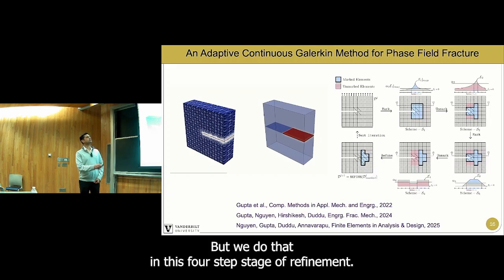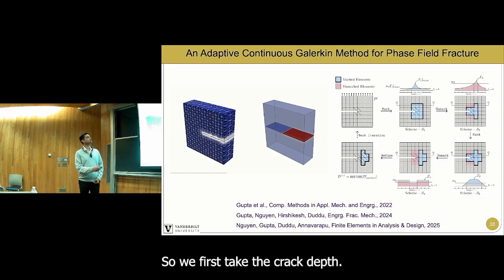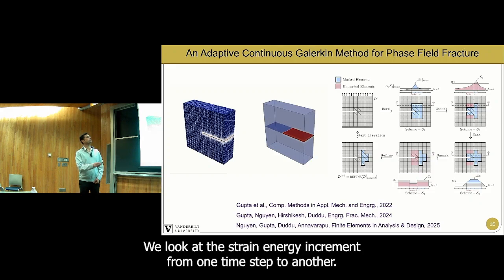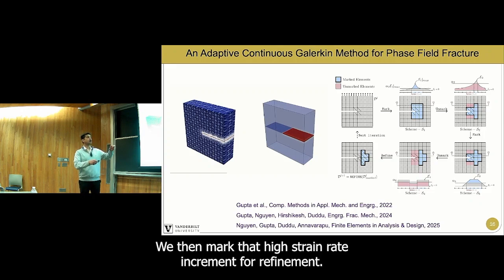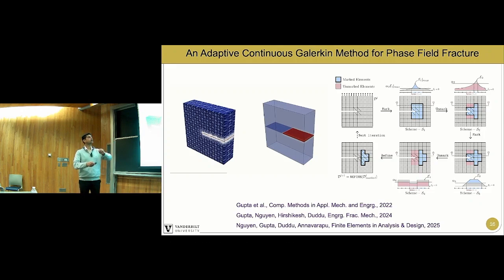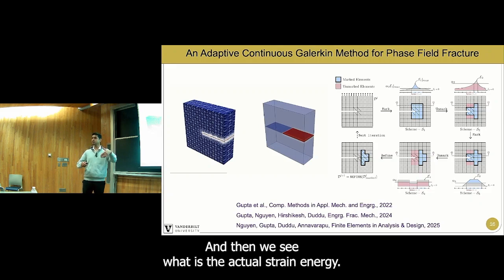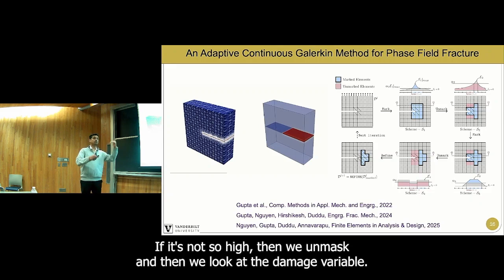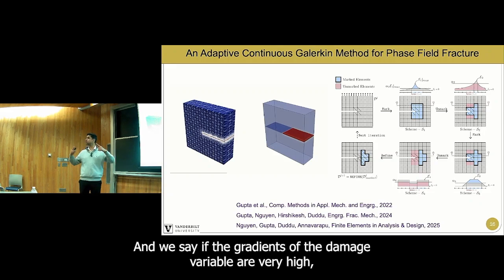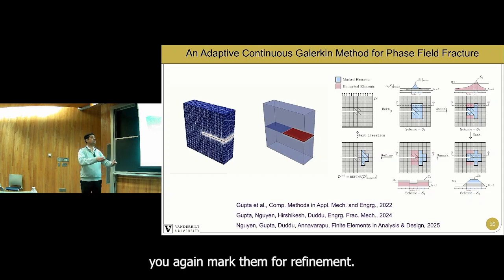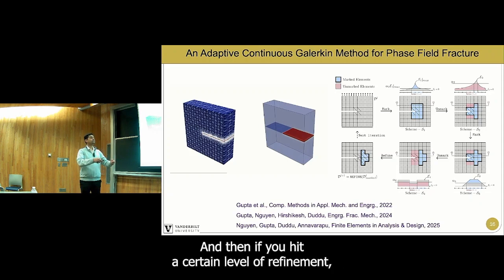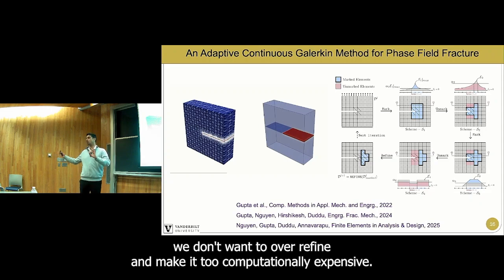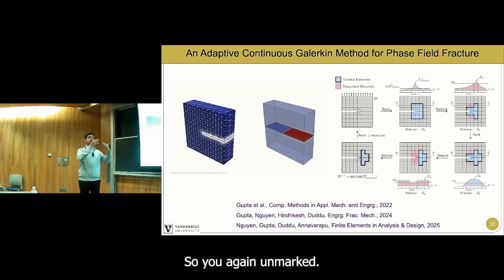But we do that in this 4-step stage of refinement. So we first take the crack tip, we look at the strain energy increment from one time step to another. We then mark those high strain energy increments for refinement, and then we see what is the actual strain energy. If it's not so high, then we unmark, and then we look at the damage variable, and we say if the gradients of the damage variable are very high, you again mark them for refinement. And then if you hit a certain level of refinement, we don't want to over-refine and make it too computationally expensive, so you again unmark them.